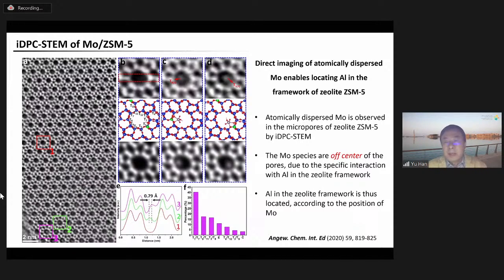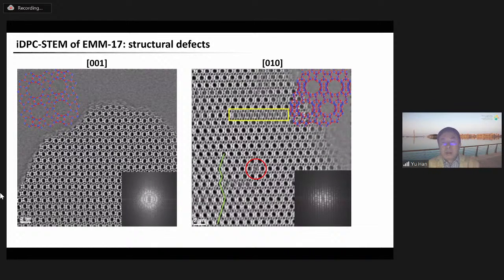And we have also used iDPC-STEM to study a new zeolite called EMM-17. This zeolite has 11-membered-ring channels, which are very rare in conventional zeolites. Most zeolites have 8-membered, 10-membered, or 12-membered rings. But this new zeolite has 11-membered rings. And more interestingly, this new zeolite contains a large number of different types of structure defects. And these structure defects can be clearly identified by iDPC-STEM. This material is rich in structure defects. You see a lot of structure defects.